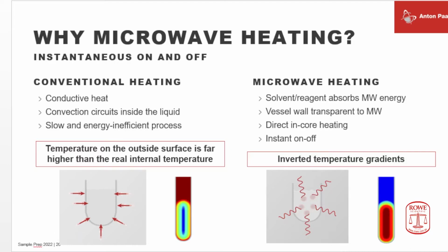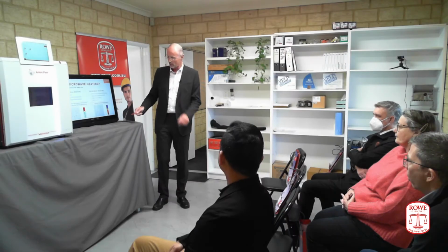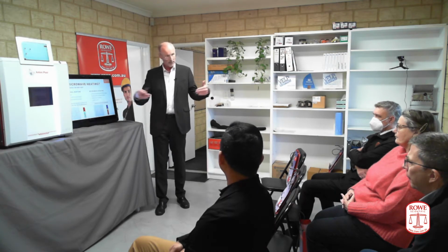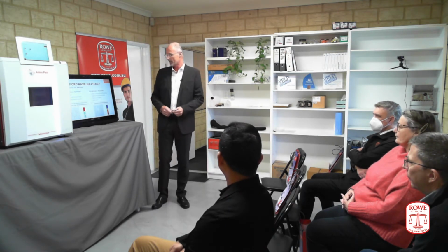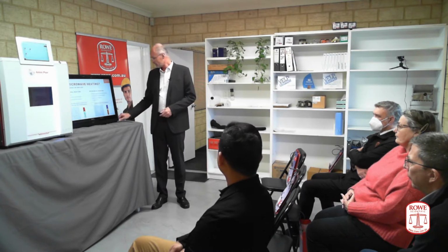It directly interacts with the liquid molecules inside the reaction vessel, and of course you must place the sample into a microwave transparent form of vessel. So microwaves penetrate through the vessel walls and interact directly with the filling content. So this leads more or less to an inverted temperature gradient. So the liquid is hottest at the inside and gets cooler to the outside. Completely contrary to as if we would apply the heat from the outside in a block digester. So this is of course beneficial.